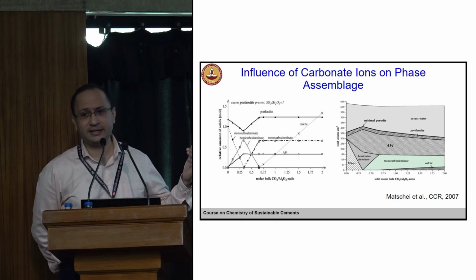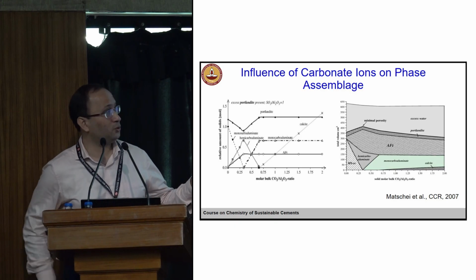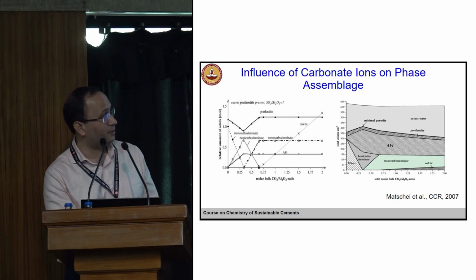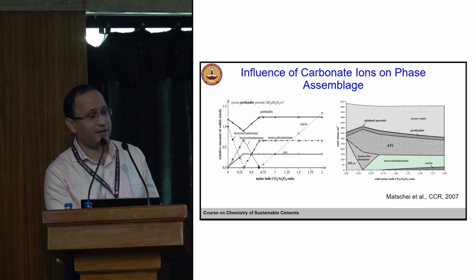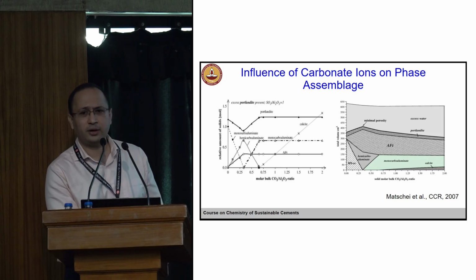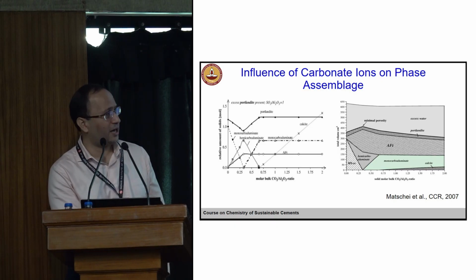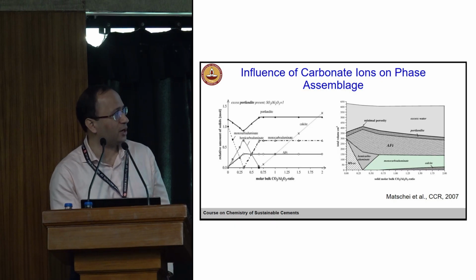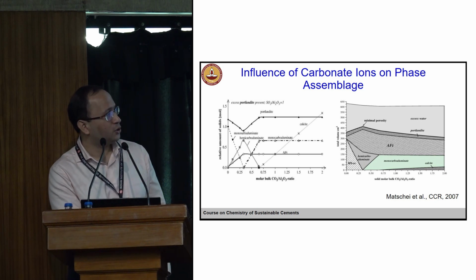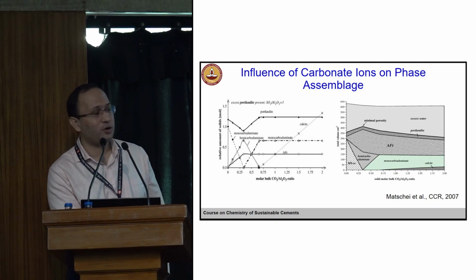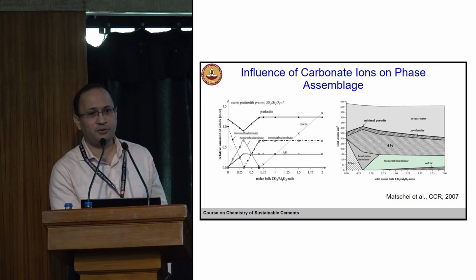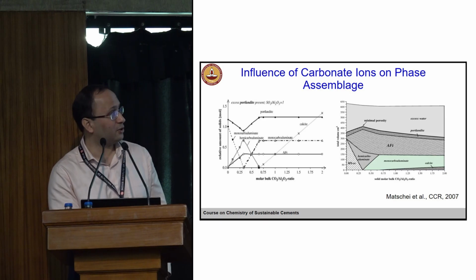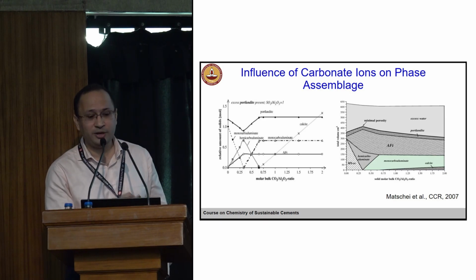But here, what we are saying is that AFt is stabilized. So you see what it does: you form initially hemicarbonate, and later on, if you have more carbonates in the system, then you will form monocarbonate. Monocarbonate is okay, but monocarboaluminate is more precise in a sense. But what it does is it stabilizes the AFt. So here you don't see a conversion of AFt to AFm. So that's also very interesting, what these carbonate ions do with respect to the phase assemblages.